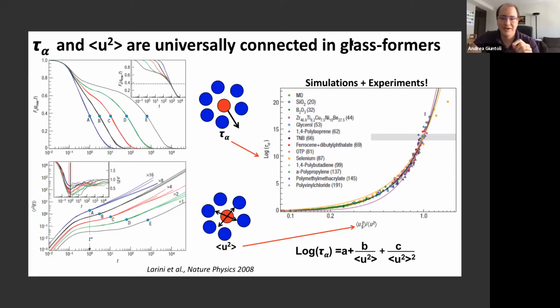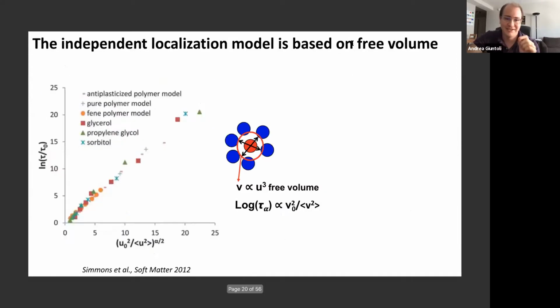And at this point, the times were ripe for these ideas. In fact, Jack Douglas and his collaborators were also working on this idea. A few years later, they came out with a slightly different model called the localization model, where instead of using the idea of the energy of the cage, they had the idea of the free volume of the cage, which again can be estimated with the Debye-Waller factor. But instead of using this law that I show here with u cubed, they also took into account the fact that this cage will have a different shape. So you have to take into account some power law exponent. So this was a slightly different model, but at the time providing similar results.